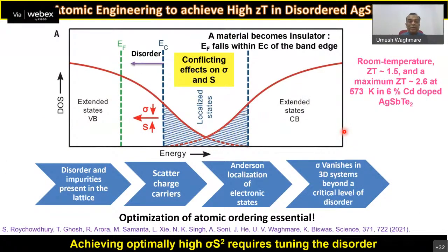So the recent work which we did was published last year in Science, and involved very beautiful science of disordered crystals in solving this problem. What is known is that typically you have a valence band of a material and a conduction band of a material, and if they overlap with each other, you have a metal. But in certain materials, you can have disorder. Disorder means atoms can be randomly decorating the lattice. And if that happens, the edge of the band states become localized. That's called Anderson localization of the states, which is localization of electrons at the band edges in adequate disorder